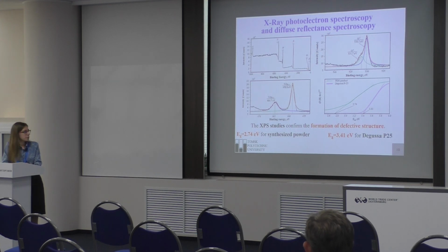The optical absorption edge in the case of the plasma dynamic synthesis product is shifted from the ultraviolet to the visible region. The difference in the band gap value is directly related to the crystal structure defectiveness of the plasma dynamic synthesis product, which appears due to the dynamic conditions in the shock wave structured medium.